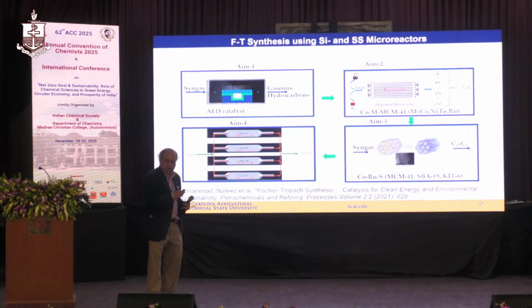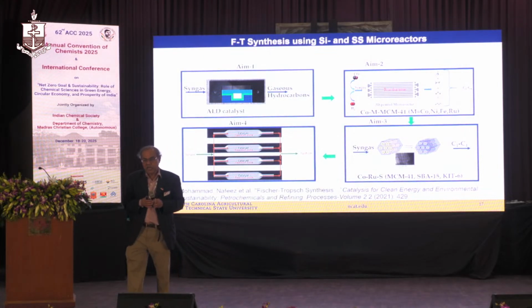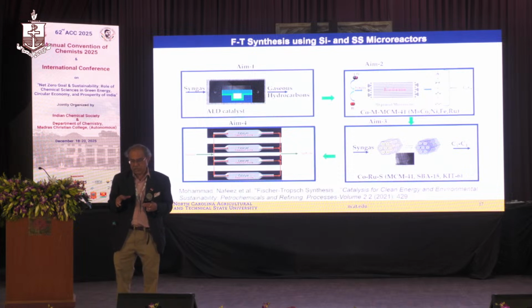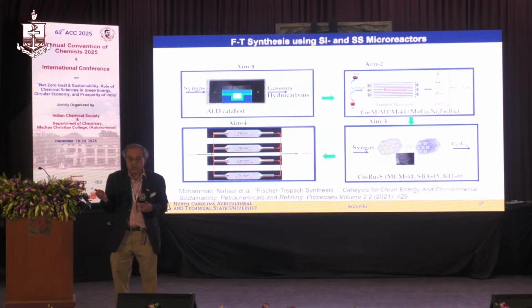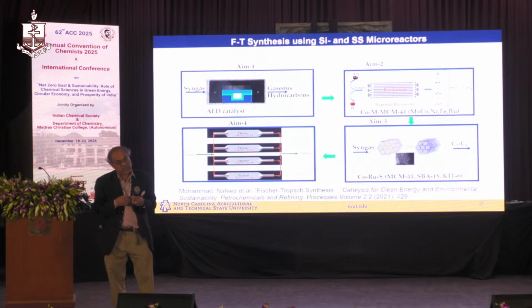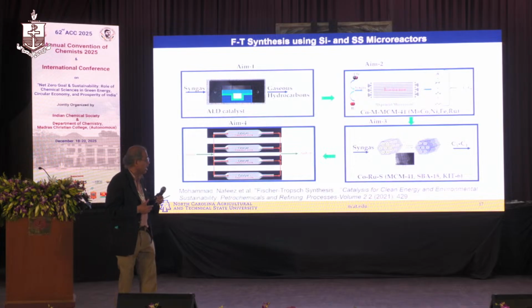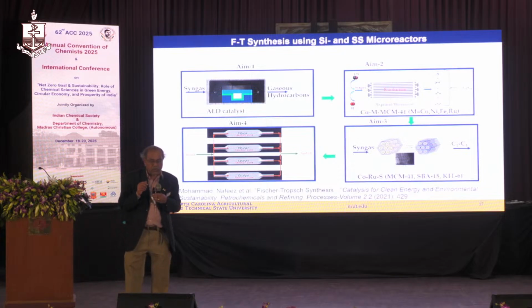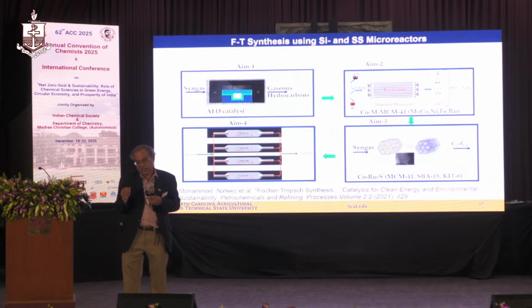So this is what we did. In the interest of time, I removed a lot of slides to fit the time. So why did we move from the silicon microreactor to the stainless steel microreactor? The reason is that for a silicon microreactor, you need a clean room, and you have to invest a lot of money to have a clean room. And the other problem with the silicon channel system is that it breaks very easily.